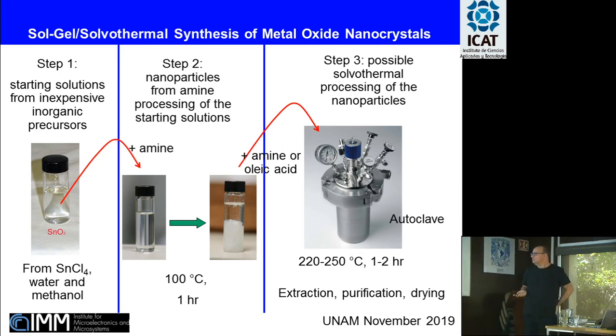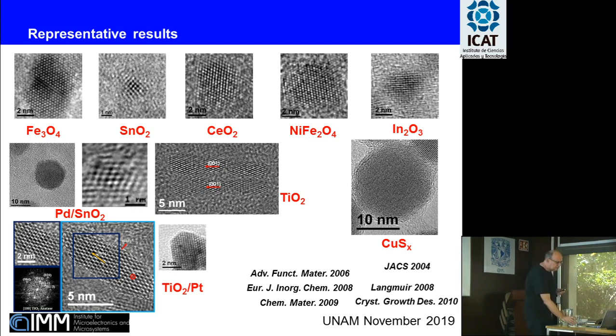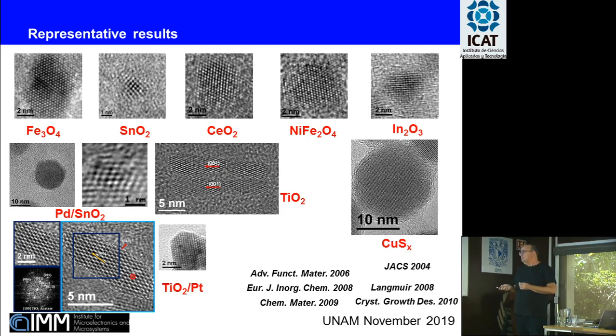After all this processing, this is an example of the materials that it was possible to prepare. So we can explore a very broad range of materials, and we will see other examples afterwards. We have iron oxide in the oxide area, titanium. We can dope with palladium, with platinum. We can prepare metal sulfides, indium oxide, and many other materials that we can prepare by this general process that was developed by reasoning onto a strange case of cadmium selenide, and by using some precursors coming out from the work on thin films. So putting everything together, we could prepare our metal oxide nanocrystals.